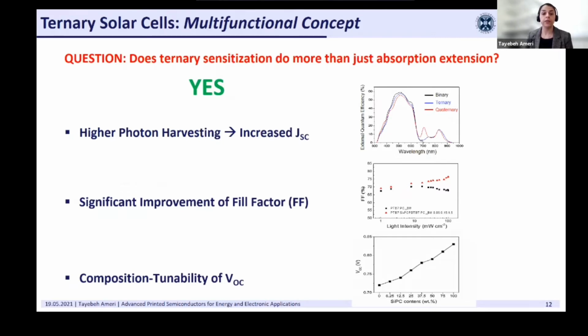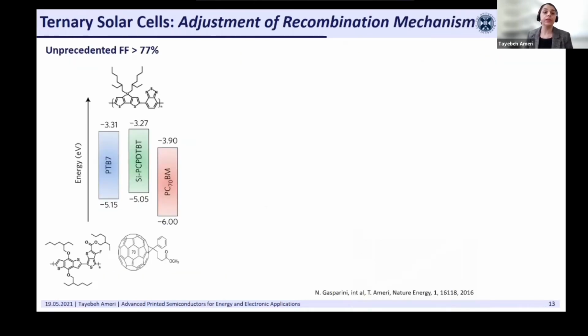But honestly, at that time it wasn't trivial to understand how introducing the third component can also improve the fill factor or open circuit voltage. As an example, here you can see that when we were introducing the same sensitizer, silicon PCPD-TBT, to a highly efficient host system of PTB7:PC71BM, we were gaining in efficiency not just because of improved Jsc, but mainly because of a huge improvement in fill factor, a fill factor over 77%, which is still one of the highest reported fill factors for ternary systems.